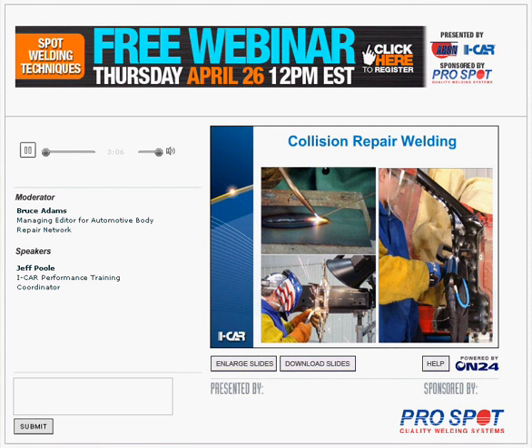Another welding method that we see limited application of right now in the U.S. is the MIG brazing process, and this uses lower heat input and doesn't melt the base metal. It's more of an adhesion process. It's not a fusion process. It does create a smaller heat effect zone, if you will, which decreases the amount of corrosion protection that's burned away. MIG brazing does require a larger footprint than MIG welding. This helps ensure joint strength.